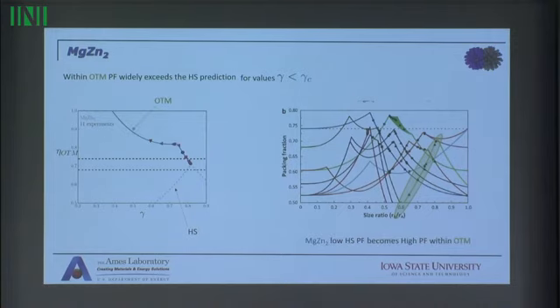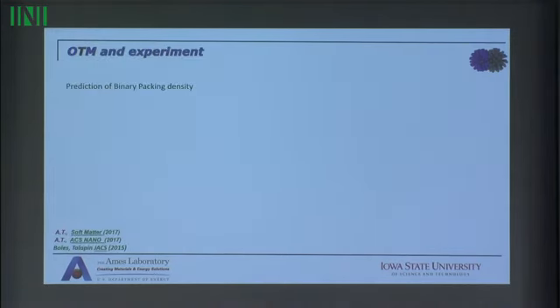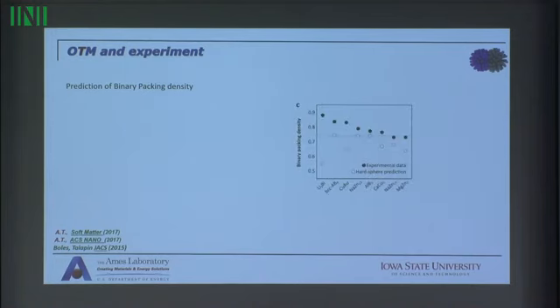So let's look a little bit at the experiment. So this is actually an experiment result. What you see here is the hard sphere prediction. So if the particles were hard spheres, this would be the prediction. This is what the experiment actually gives us. And now when we put the results for the OTM model that we just developed, we realize that without any fitting parameters, we are able to nail each and every one of the separations for this particular system.